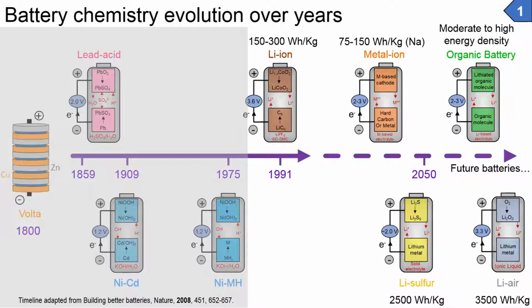Then, lithium is scarce. It's not that abundant. You can still keep the same configuration, which is metal ion, and shift to other, more abundant elements. So we can talk about sodium ion, for example. And here there is already a commercialized sodium ion battery in France from a company called Tiamat Energy, and they can provide sodium ion batteries with 75 to 150 watt-hour per kilogram, with a good power density as well. Then you have the lithium sulfur and lithium air batteries.